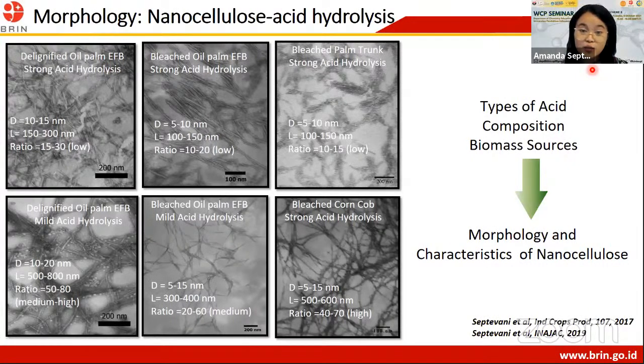But interestingly, we also work with other resources such as corn cob. With the corn cob, even though we use strong acid hydrolysis under the same conditions, we can get a high aspect ratio, where the bleached corn cob usually contains high hemicellulose that can influence the morphology of the nanocellulose after the hydrolysis.